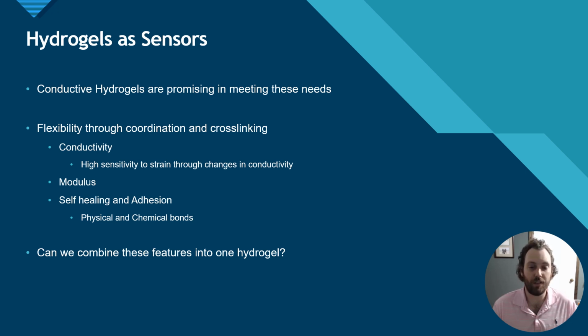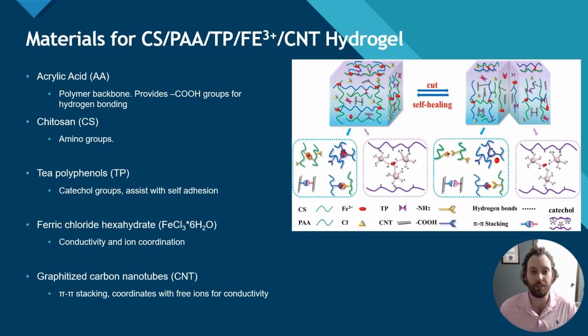My group set out to see if we could feasibly come up with a novel compound that could combine and modulate all four of these properties into a potential strain sensor. In order to do that, we had to be strategic about the materials we pick. Starting with the carbon backbone, we sought to develop a complex matrix of intramolecular forces. The backbone, built from acrylic acid, will introduce a large number of carboxylic groups, which will contribute to hydrogen bonding. Chitosan was also introduced. This gives us amino groups to our compound, and we'll discuss this when we get to our ions. We'll introduce a complex ion coordination.